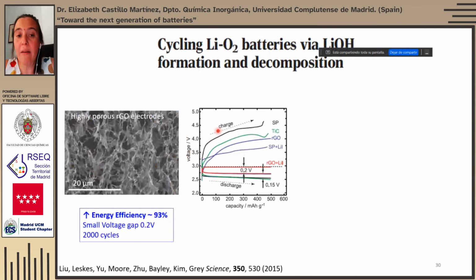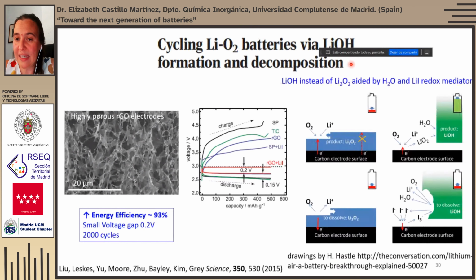A breakthrough in lithium-air batteries came in 2015 in the group of Professor Grey, when they used highly porous reduced graphene oxide electrodes, as well as a lithium iodide redox mediator and some unwanted amount of water, well, unwanted at the beginning, but then wanted and controlled, in which instead of forming lithium peroxide, it formed lithium hydroxide. If we form lithium hydroxide, we are getting 4 electrons per oxygen molecule instead of 2 electrons, and the capacity can be increased further. And the presence of the lithium iodide redox mediator helps on decomposing the lithium hydroxide product as well, as would be for the lithium peroxide.